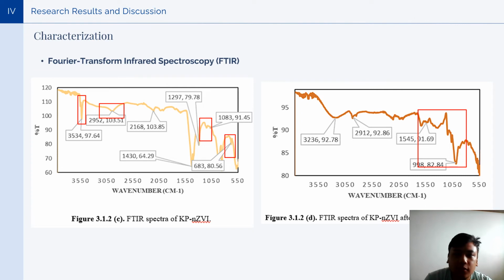In figure 3.1.2c, the narrowing of the band at 3534 per centimeter indicates the possible interaction of the hydroxyl group of the sweet potato peel starch with the iron nanoparticle. Furthermore, the peak at 683 per centimeter presents improved absorbance, implying the interaction between iron and starch during the encapsulation process.